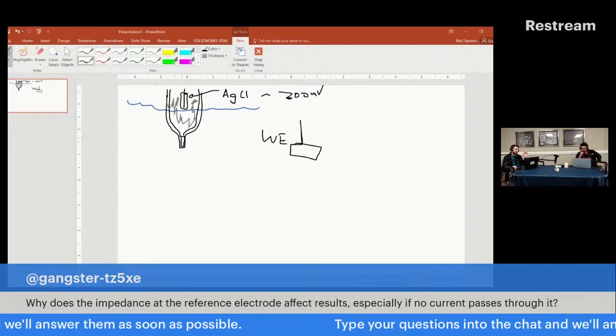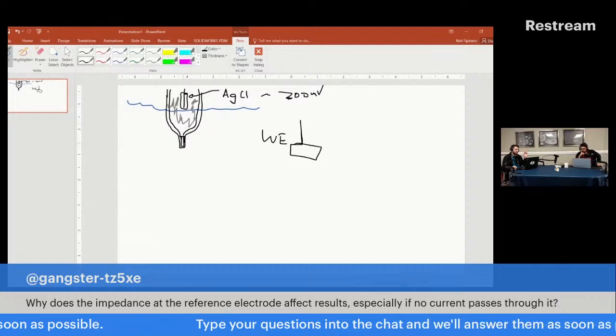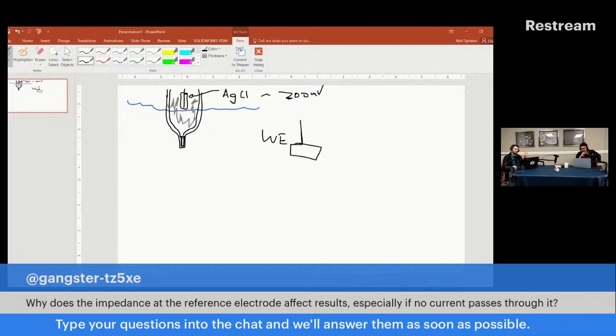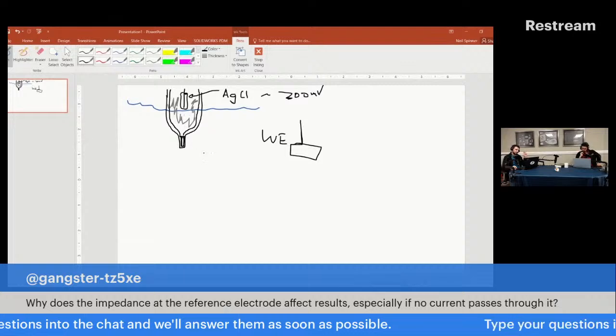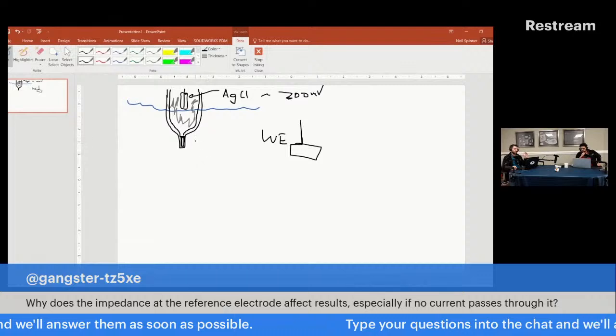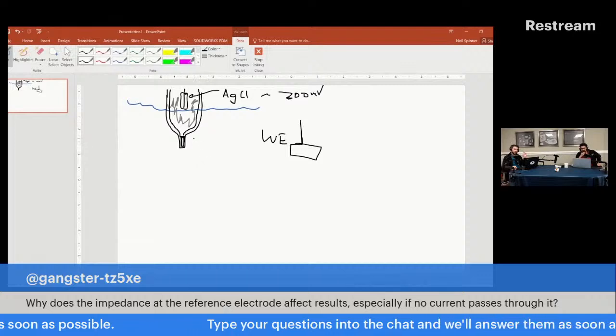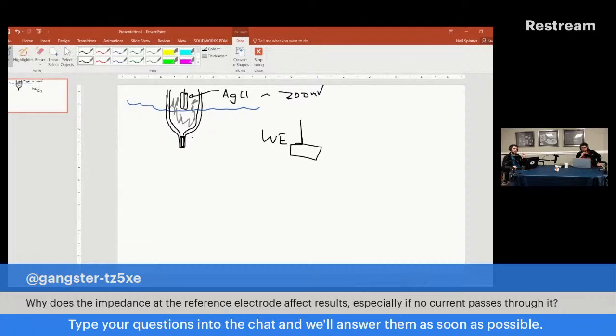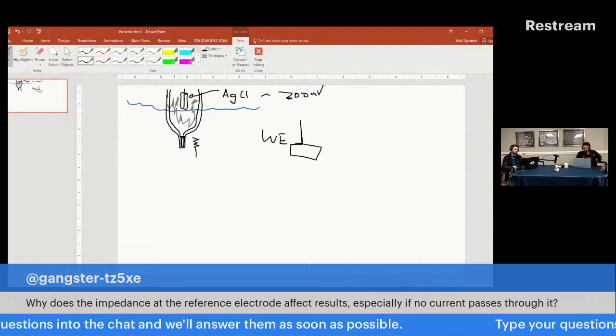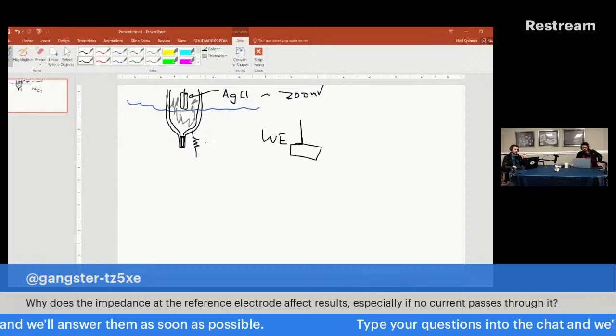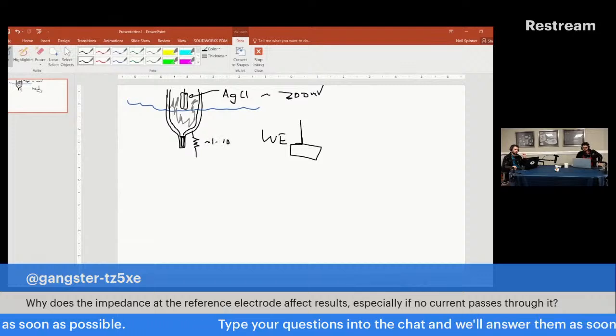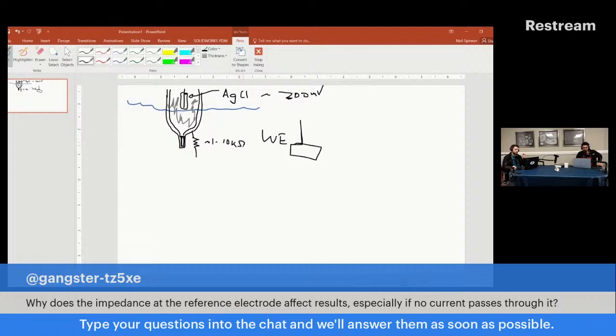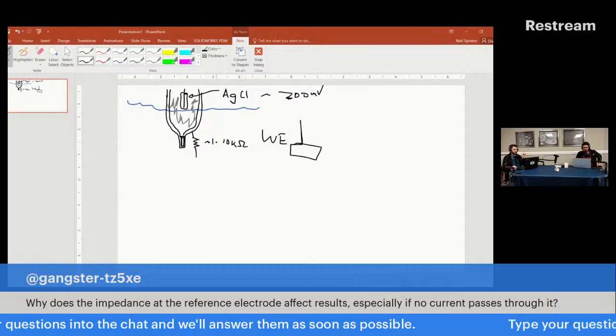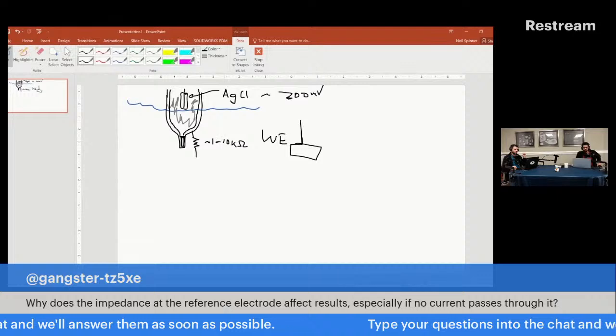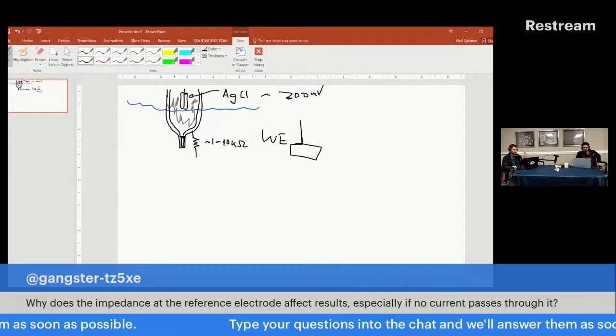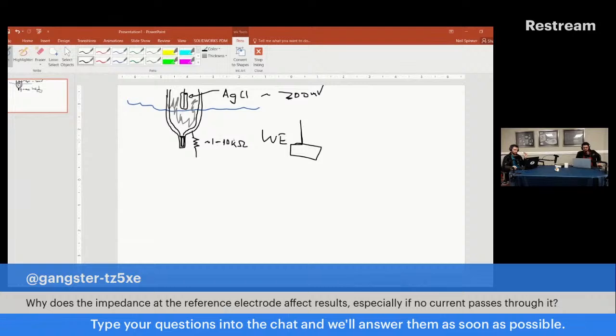And so we have to use this frit. This frit right here basically blocks bulk diffusion between the inside of the reference electrode and the bulk solution. That is what is associated with typically the amount of impedance. The frit has a resistance associated with it, and it's usually somewhere between 1 and 10 kilo ohms. Okay. Now here's why at high frequencies we have a problem, and why it causes issues with the potentiostat.